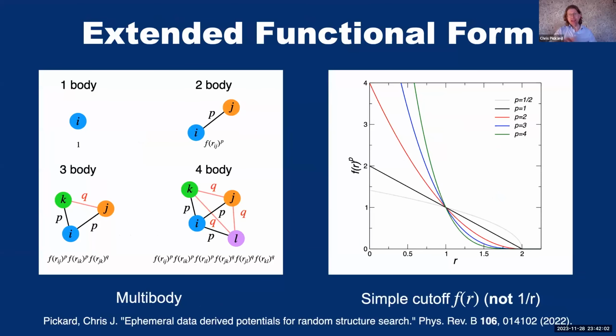Now, to be explicit, in the case of Lennard-Jones, all the functions are of the form 1 over r to some power. Now, I generalize this to an arbitrary function of r raised to some power, and because in the end we want our potentials to be cut off in space, I bring that cutoff into this function right from the very start. So instead of 1 over r raised to different powers, the function that I raise to different powers is this black line on the right-hand side, which is just a straight line from 2 to RC. So RC is the cutoff radius, and beyond there's no further contribution. And you can see that as you raise that simple function to powers, it looks a little bit like what you might get with a 1 over r term. It's not exactly the same, but it has a similar kind of functional form.